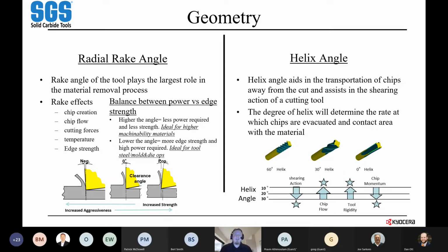So the higher the angle, the less power is required to run that cut. It's going to cut more efficiently. You can run it on a lower horsepower machine or a lighter setup, and you can get good results out of it. But it is going to have a lower strength, so it's going to be a sharper, more brittle edge that can fail. And so this makes it ideal for higher machinability materials.